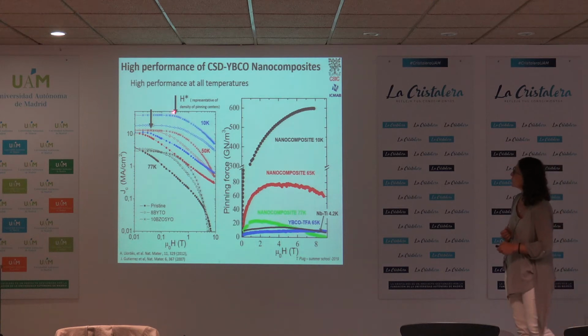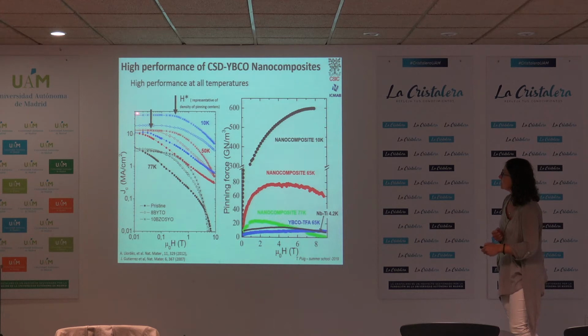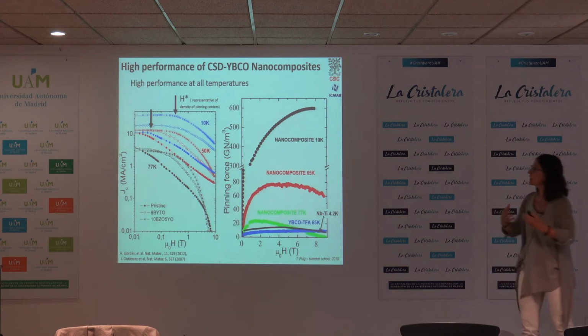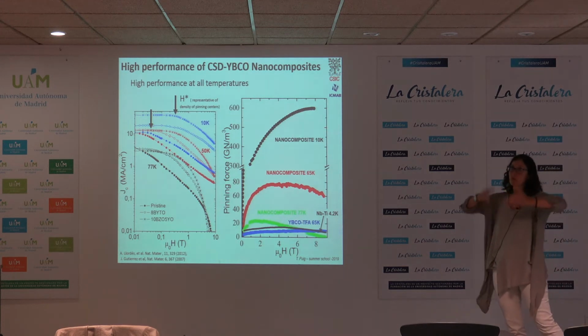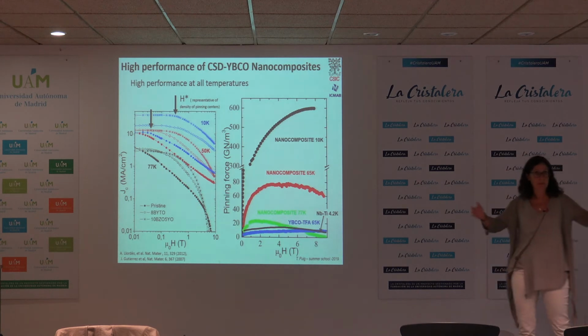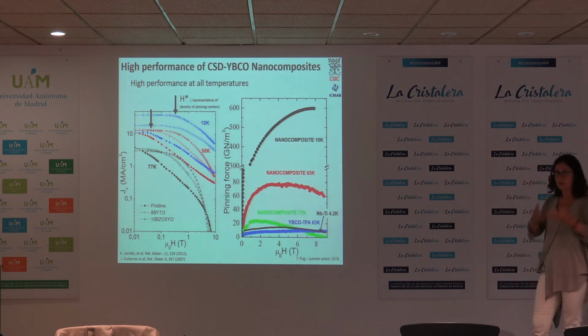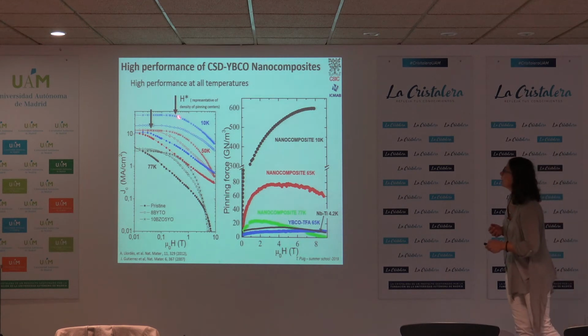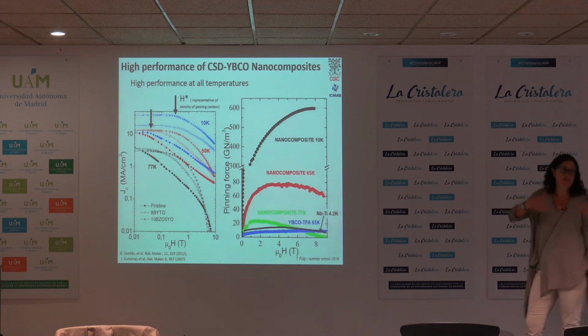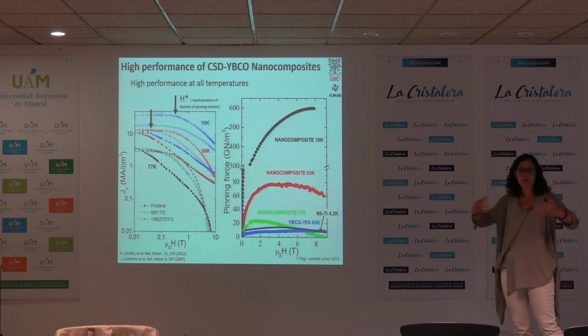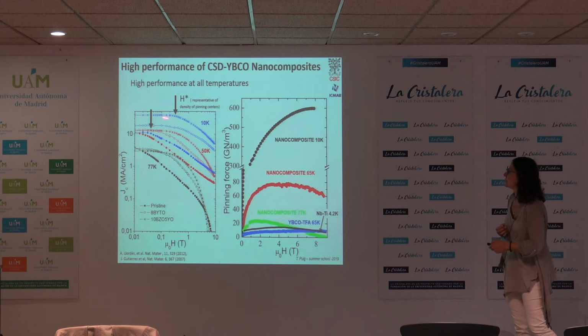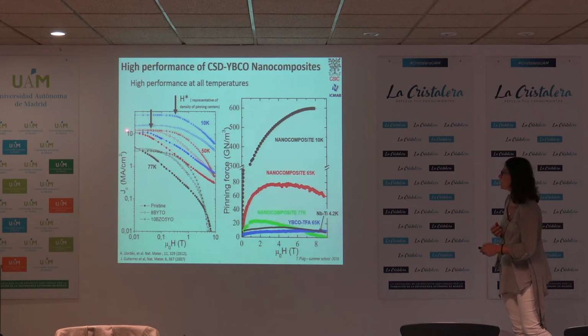In fact, I want you also to concentrate on what we call the irreversibility field, the place where this plateau of JC starts to decrease, because this is somehow representative of when all the vortices will be at pinning defects, okay? So we will not have a collective behavior of vortices, and therefore it can be emulated as something like a density of pinning centers. So if we have a higher number of pinning centers, this field is expected to go higher, okay? And this is what we see, in fact, if we compare a non-nanocomposite with a nanocomposite at any of the temperatures, here or here or here and here.